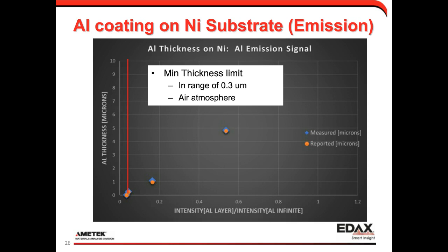And as you go sort of below the 1/4 micron, we're reaching a limitation in our precision in terms of getting meaningful results of measuring aluminum in an air atmosphere. So aluminum is a relatively low energy X-ray line, and as it goes from the sample to the detector through the air path, our signal gets scattered, and so we lose sensitivity. Our minimum thickness range is around 0.3, somewhere in a couple hundred nanometers type range. If you want to bump that up, we could go over to, let's say, a vacuum-based system where we pull vacuum on the sample and then we make the same kinds of measurements. And EDAX has higher-end instrumentation for that kind of measurement as well.